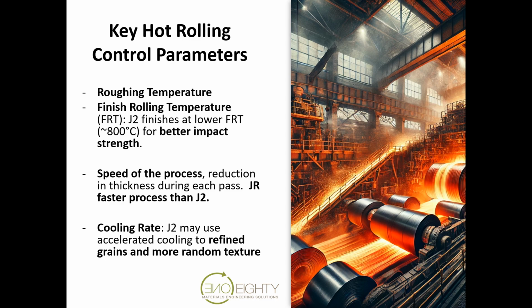So they have to, because they are rolling at a lower temperature for better grain structure and microstructure, and therefore better impact strength, the whole process takes a longer period of time because they're not able to put in the same amount of strain during each pass as they are when they roll JR material. So the speed of the process in reducing the thickness during each pass, JR is a faster process than J2.